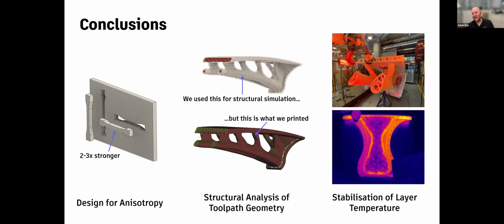Turned out that because we're only flowing 20 pounds an hour, and because the structure is so big, we really needed to be flowing a lot more material. So our layer temperatures were generally right at the edge of where we wanted them to be, or a little under sometimes. So we took a bunch of infrared heat lamps, the same ones you use for curing paint on cars and things like that. And we attached them to the cell and on the robot track and around there so that we could stabilize that layer temperature to reduce the warping and keep us in the range that would produce good layer bonds.